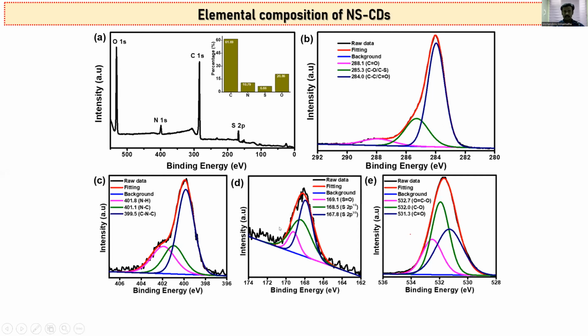Another one is the sulfur peak. In the sulfur peak we can get S double bond O, and also 2 different sulfur forms, S2p 1/2 and S2p 3/2 elements. Okay, and finally the oxygen spectrum appears at around 530 to 532 electron volts. The fitted maxima correspond to what we confirmed previously: C double bond O. Here we can also confirm C double bond O and single bond O, and also O double bond C with a single bond O. This is the XPS survey spectrum.